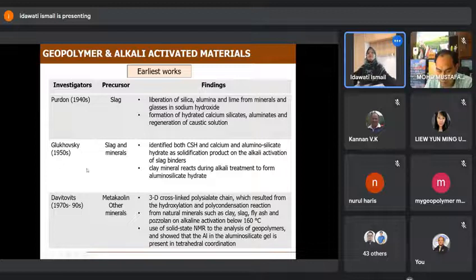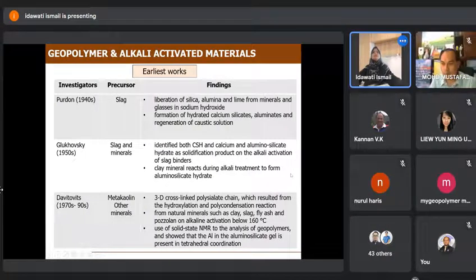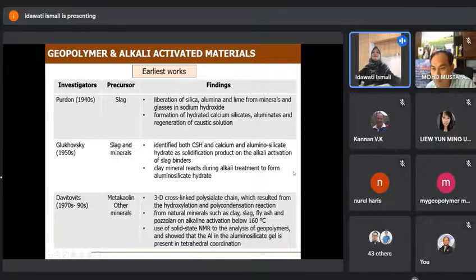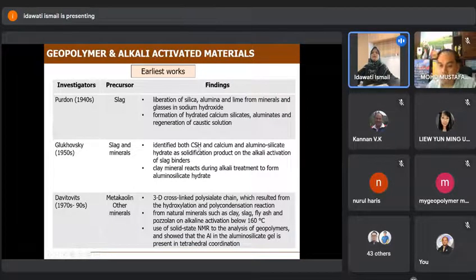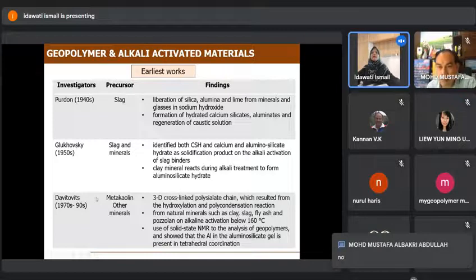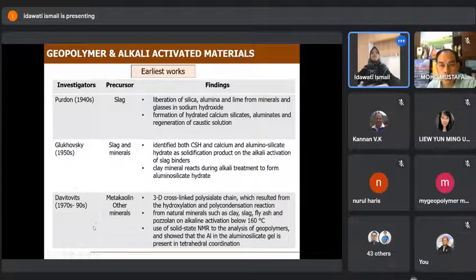Then Glukhovsky in the 50s also did something similar with other minerals and also identified CSH in the system and some calcium and aluminum silicate hydrate as solidification products on the alkali activation of slag binders. And clay minerals react during alkali treatment to form aluminum silicate hydrate, also a hardened binder and very similar to the structure of CSH in cement binder. And of course, we can give credit for geopolymer to Davidovits, who started in the 1970s and continued until today